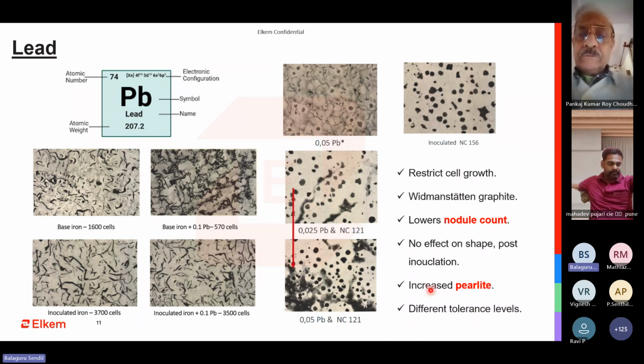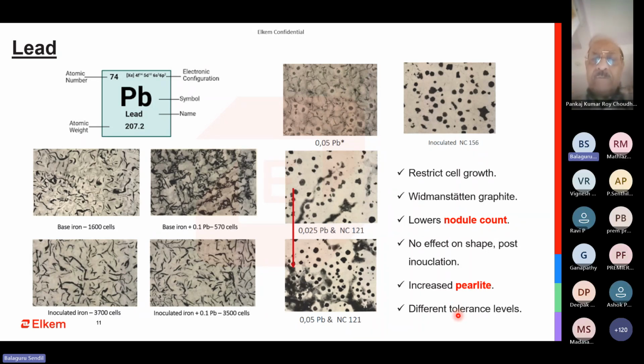And the tolerance level can be different. How much lead can your liquid metal tolerate? It can depend, as I told, on the factor that you can measure, which is the nodule count drop. But if you have inbuilt methoding support, you are giving a larger feeder, or a bigger riser, or the methoding has been done in such a way that these variations can be accommodated, then it cannot be as severe as for somebody who is operating at very thin margins.